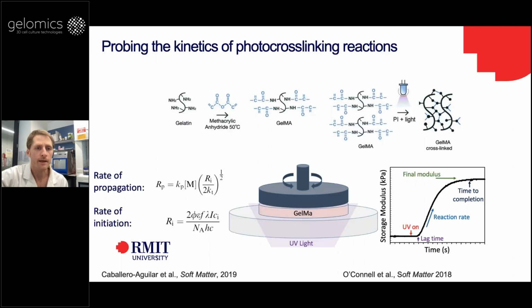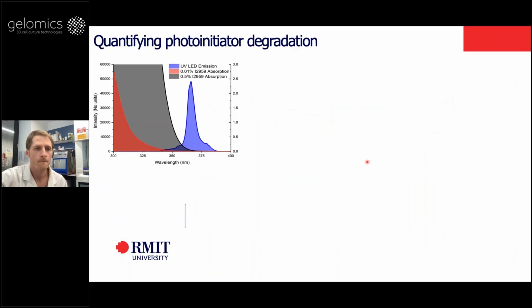Oh yeah, by the way, the data I'm talking about here is generated in a rheometer, where you've got a quartz plate on the bottom, and you shine the UV light up from underneath, and that's how you can monitor the change in stiffness as a function of the light exposure time or intensity and so on. So, at the very start, let's start with the light.